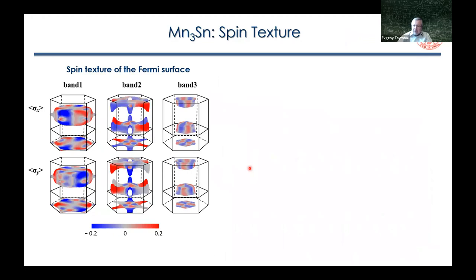So if you do a calculation and compute the shape of the Fermi surface, we find that there are three bands, band 1, 2, and 3, crossing the Fermi surface. Similarly to the previous plot, we show here in color the projection of X and Y components of the spin on these Fermi surfaces. And on the bottom, we show a projection of the Fermi surface itself on the 0001 direction. So obviously, as you can see, we have a spin-dependent Fermi surface, and as a result, we should have transmission which should depend on the Néel vector orientation.